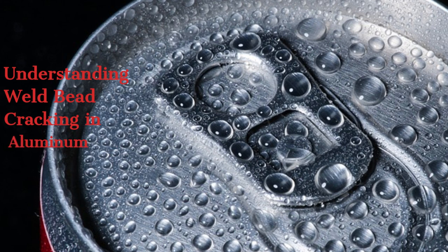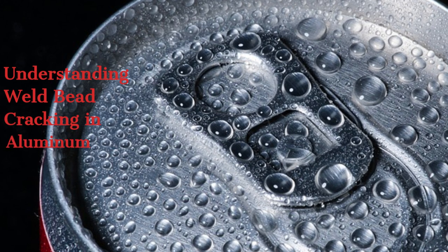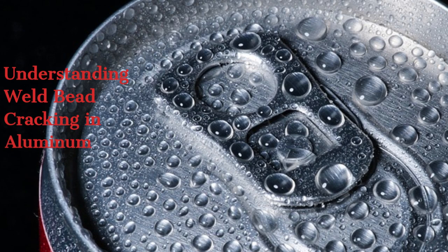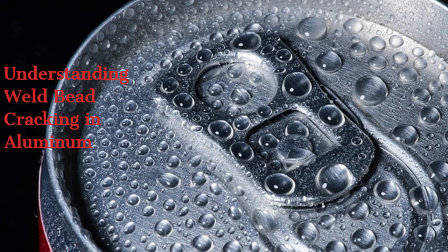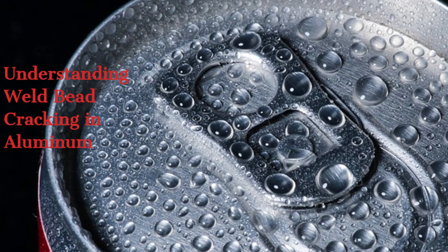The second challenge is hydrogen-induced porosity. Hydrogen loves molten aluminum, like a moth to a flame. But once the aluminum solidifies, it's like, personal space, and the hydrogen gets trapped, forming pores. Think of it as unwanted house guests who refuse to leave because they are so in love with aluminum, and when they are pushed hard, they create pores.